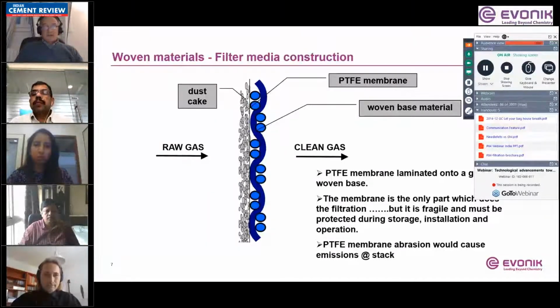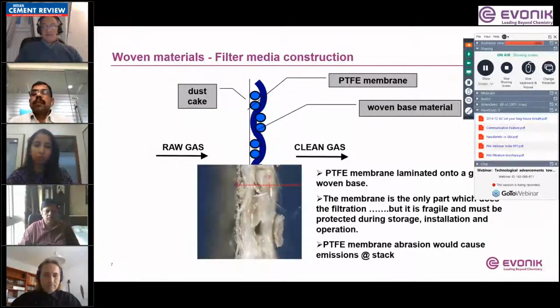You see also that during operation and after cleaning, the PTFE membrane remains almost totally exposed to the gas flow. It doesn't retain, indeed, much dust, as you see from this picture.